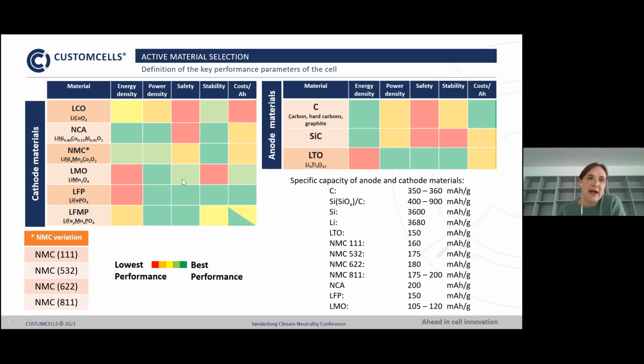So everything started with the LCO, the lithium cobalt oxide, but all of us know that cobalt is not only a rare material, but also is sometimes gained by non-ethical or ethically problematic working conditions. Therefore, the recent trend is to use a material called NMC or NCM. It really depends on the overall buildup of the material. It is the same building block as the LCO. It's a lithium cobalt oxide, but the cobalt is diluted with other metals, nickel and manganese. This is done due to several reasons.